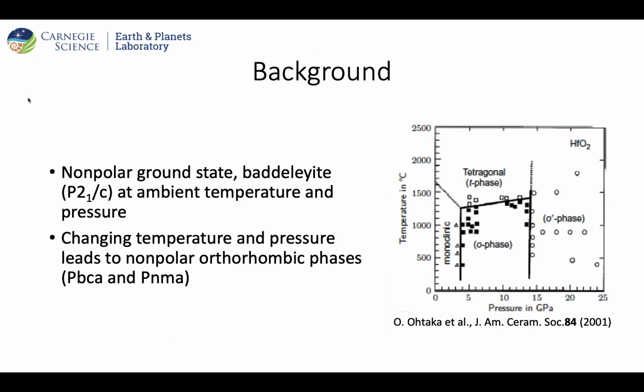I'm going to go through a short background, and you've seen this from the earlier presentation, the phase diagram, temperature and pressure, of Hafnia. At high temperature, we have tetragonal, at about 1800 degrees Celsius. Then if you lower it to room temperature all the way to 0, we see the monoclinic phase, or the Baddeleyite phase. And if you increase pressure, going to the right, you have the PBCA, and if you increase it furthermore, you find the PNMA structure. So nowhere in this temperature-pressure phase diagram do we see a ferroelectric or polar phase.